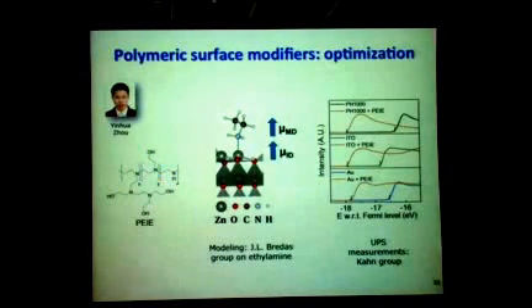When we started dipping ITO or other electrodes into a dilute solution of a branched polymer like this, the shifts observed in the vacuum level in UPS experiments were huge, up to 1.5 volts. You can see this is the result on ITO, so you have a huge shift.